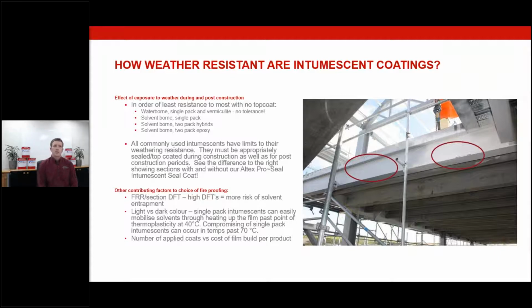You've got some other factors with regards to the choice of fireproofing, your fire rating on the section DFT. So with regards to low Hp/A steel or light section steel, you're resulting in high dry film thicknesses. With high dry film thicknesses, particularly with single packs, you've got more risk of solvent entrapment. That's the other common mode of failure that you'll see for intumescent systems.